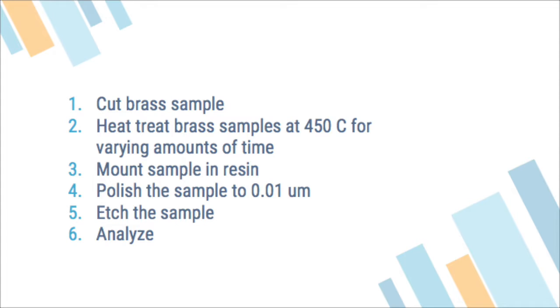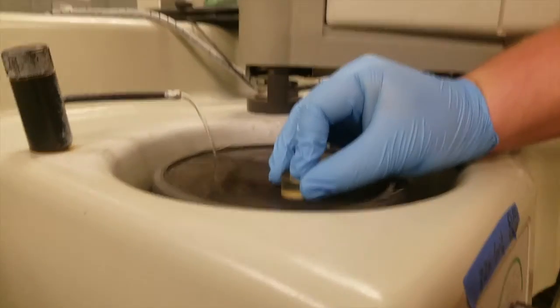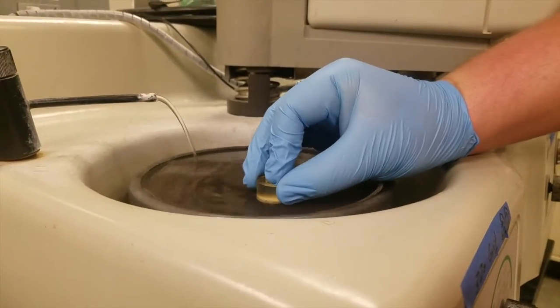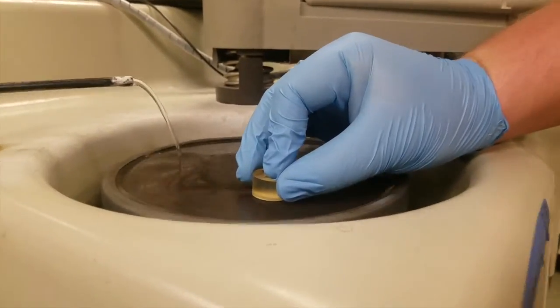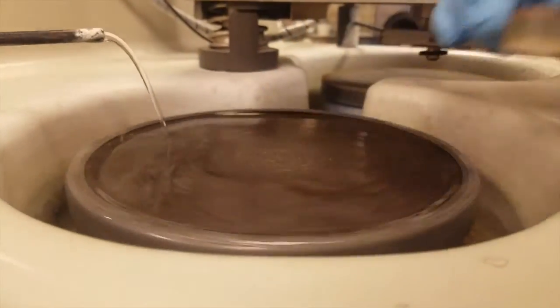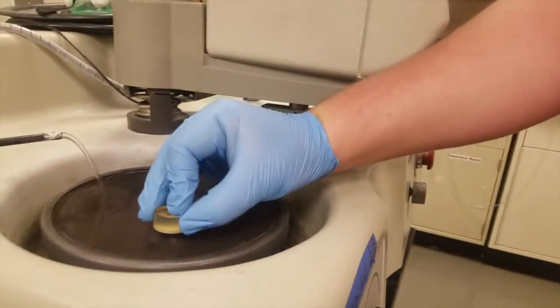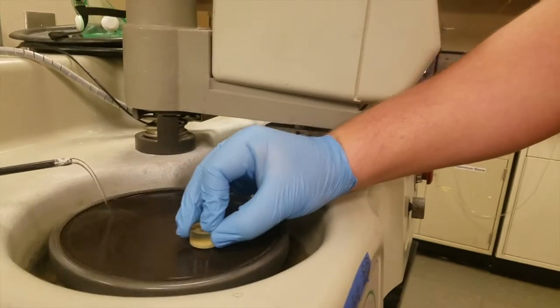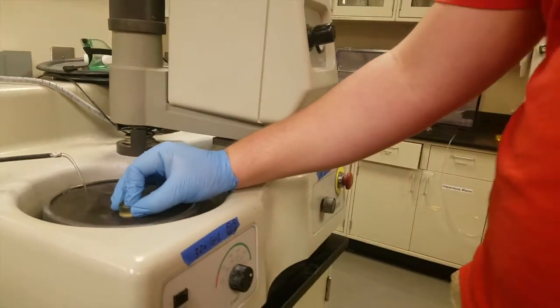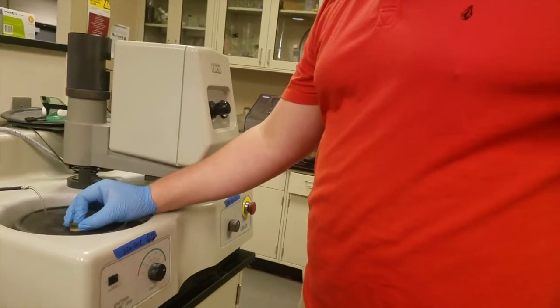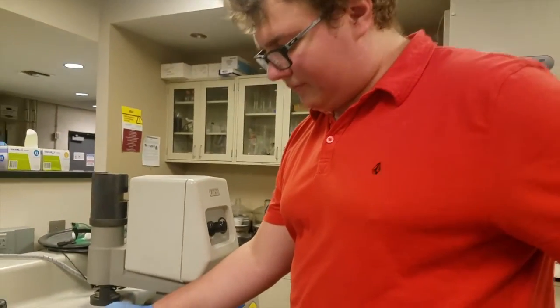The mounted samples are then removed. They are ground to remove excess resin. They are then polished using the previously mentioned grit papers and polishing suspensions. They are held to the polishing paper with medium even pressure and turned 90 degrees every minute until the polish is even. When polishing the sample with the 320 grit paper, make sure the surface is flat and scratches are uniform before moving on to the next grit size.